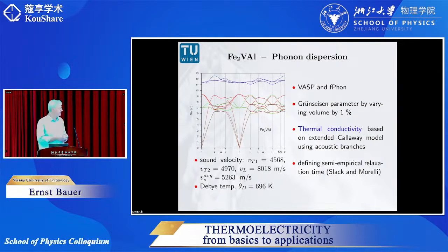Finally, from this DFT section, we can calculate the phonon dispersion. Plotted here is the phonon dispersion as a function of energy, here represented in terahertz. 1 terahertz is about 50 Kelvin. You can see we do have acoustic phonons, and again, the velocity of these phonons is proportional to the slope of these phonon branches. The other phonons here are the so-called optical phonons.